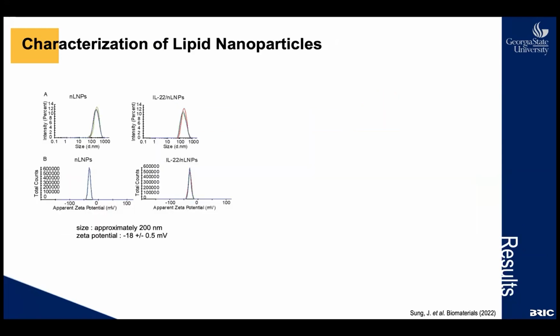Now we have both IL-22 mRNA and lipid nanoparticles ready to be used in the experiment, but before we apply that to this delivery system, characterization of the lipid nanoparticle is an essential part of the study, because we need to know what goes inside the system, and it could affect the efficiency and efficacy of the drug we deliver. First, we measure the size and the zeta potential of the blank and the encapsulated nanoparticles. Size of both blank and encapsulated lipid nanoparticles was approximately 200 nanometer diameter, and the zeta potential was about -18 plus minus 0.5 millivolts. The zeta potential is a measure of net electric charge on the surface of the nanoparticle, and it is crucial for determining the stability of charged particles.